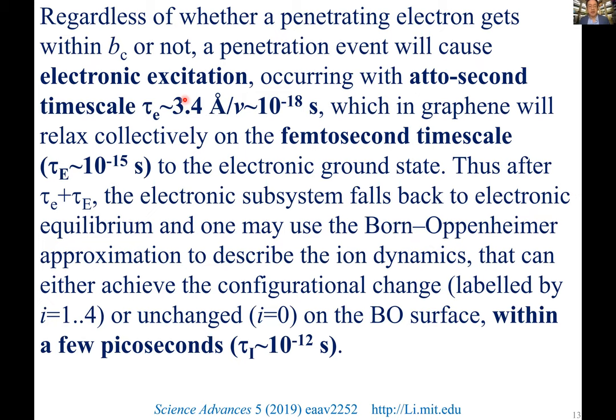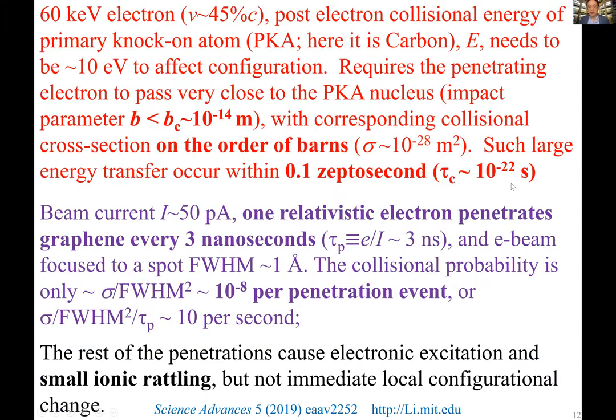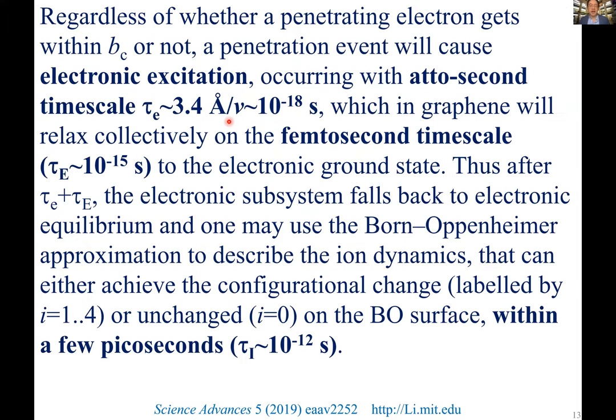If you divide the thickness of graphene by the speed of the electron. And then there is also this electronic relaxation, which we assume for graphene is rapid. So it's a femtosecond. So you have a very nice separation of time scales. The collision is 10 to the minus 22. The excitation is an attosecond, and then the electronic relaxation is a femtosecond.